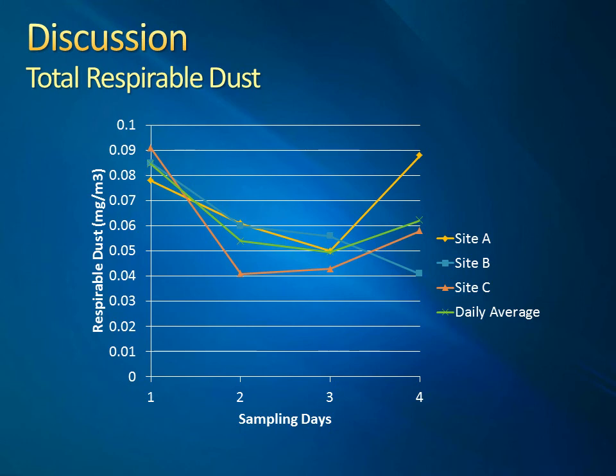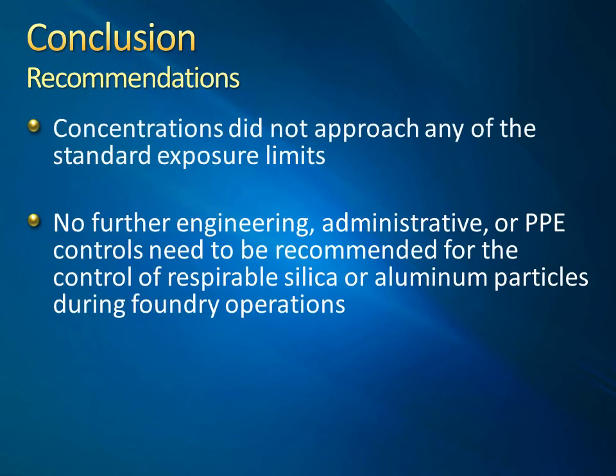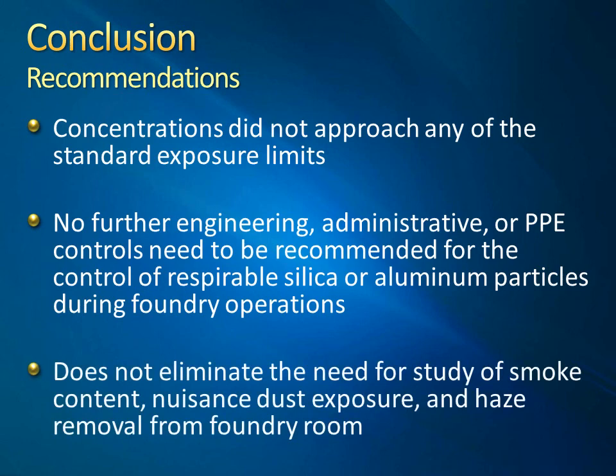The increased respirable dust concentrations during the first sampling day was probably due to the time spent moving equipment and buckets of the green sand, positioning all of the goods to start the actual analysis during the initial casting process. Based on these comparisons, concentrations did not approach any of the standard exposure limits. No further engineering, administrative, or PPE controls need to be recommended for the control of respirable silica or aluminum particles.